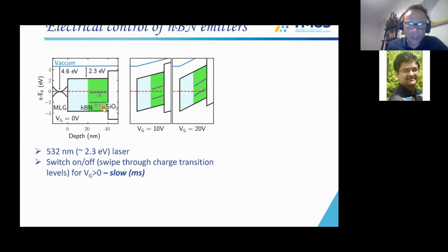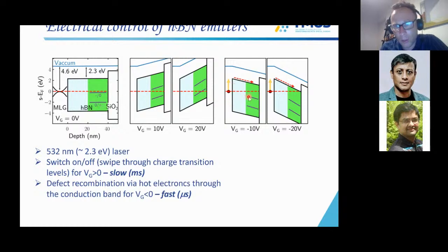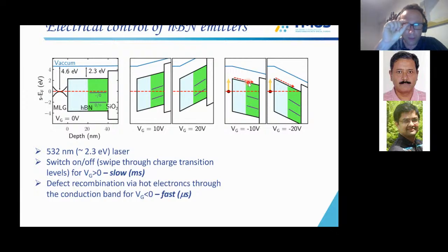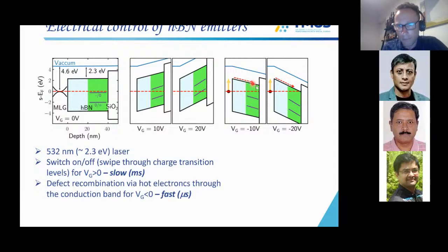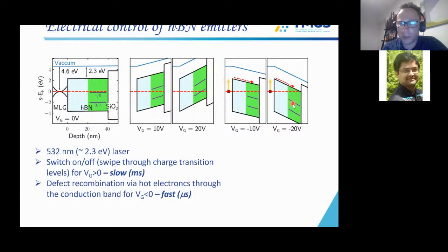So remember that these are quantum systems that only operate at one specific charge state, for example, 0 or -1. And when you go to the negative bias, obviously you're not going to cross anything anymore. But what happens here is that, again, we apply 2.3 eV, which is the green laser, and you generate hot electrons because the junction is very, very small. It's only several tens of nanometers, and they can then recombine on your emitter level. And of course, as you increase the negative bias, you increase the recombination rate, which makes the defects brighter and brighter. So one proof that this mechanism is actually working is the difference in rate.